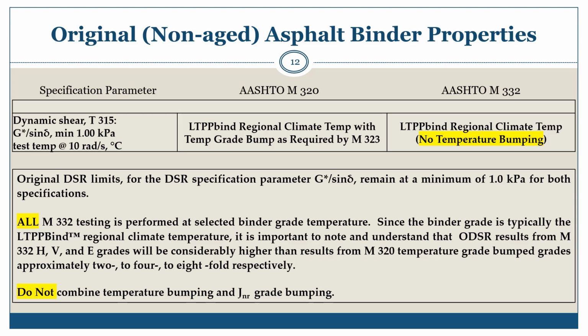It is important to note and understand that ODSR, original DSR results from M332 H, V, and E grades will be considerably higher than results from M320 temperature grades, approximately 2, 4, or 8-fold respectively. Temperature bumping M320 and JNR M332 grade bumping should not be combined, as this will require overly stiffened asphalt binders.